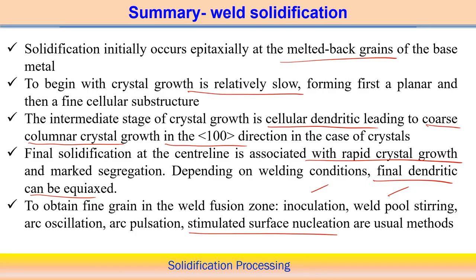And of course, stimulated surface nucleation is also helpful to start nucleation at several positions and at a high rate, such that at the same time many nuclei start at different positions. Then they try to grow, and when competitive growth occurs almost equally from all the different zones, they create a very fine grain structure associated with the welding process.